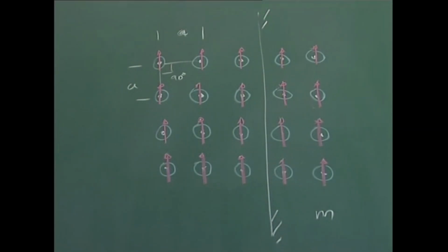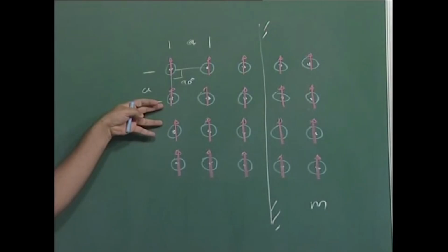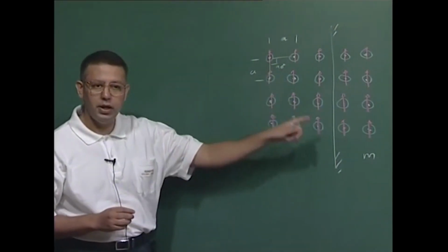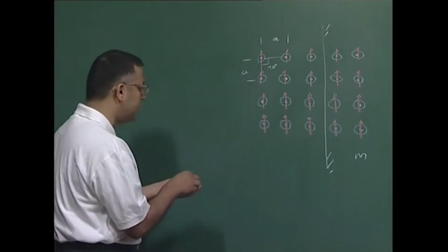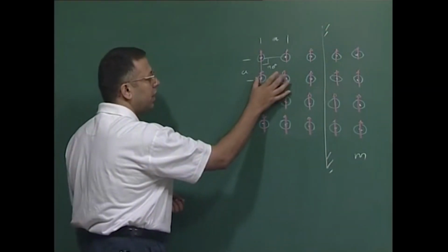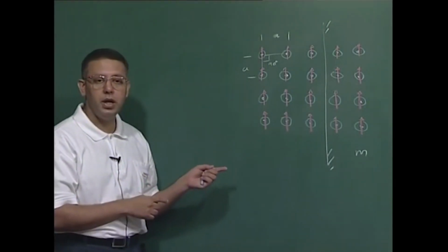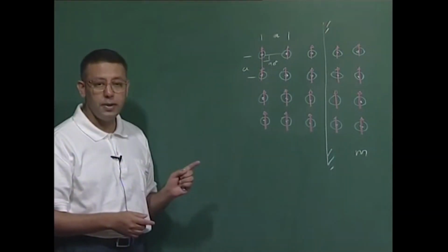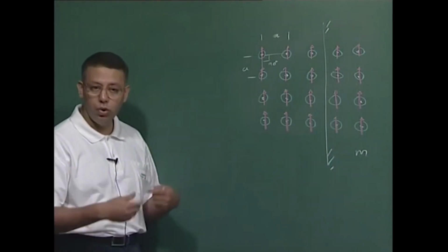But the important question I am asking, which is relevant to your question, is that can this magnetization moment itself change the lattice parameters, in addition to the fact that if I look at the symmetry, we know it is a square crystal. It could so happen, because of the magnetization moment, there could be a selective change in the lattice parameters. For instance, either there could be a contraction or expansion along this direction, because now the physical property is aligned, right. So there is no random and there is no averaging, and if that happens, even the lattice parameters would change, and in that case automatically my four-fold axis would be lost and it would be a crystal of lower symmetry.